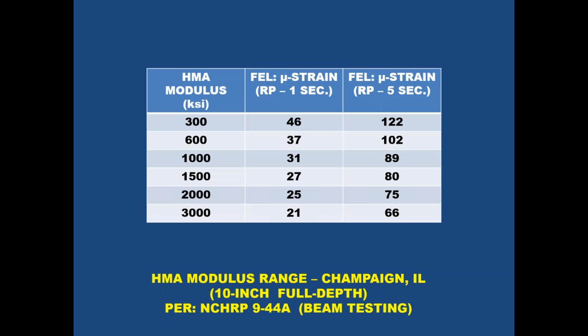I ran this particular procedure they proposed for a section here in Illinois, a 10-inch full depth pavement, various moduli values. If you have a 1 second rest period, that's the fatigue endurance limit in microstrain. You got a 5 second rest period, this is what you get. Considerable difference. Factor of what? 3, something of that sort. So that's of some significance.